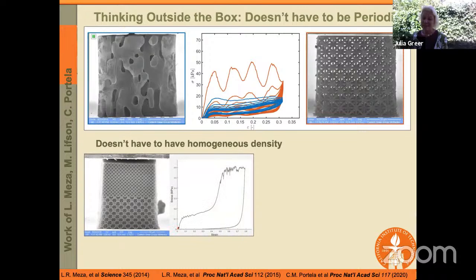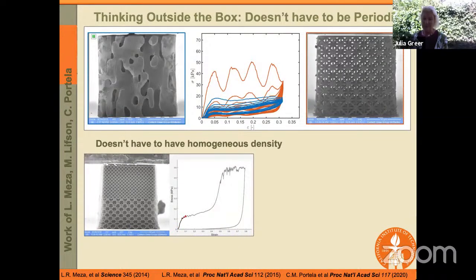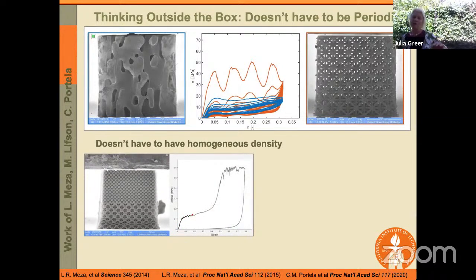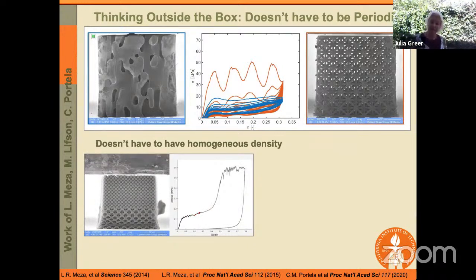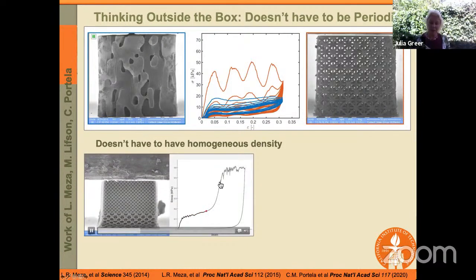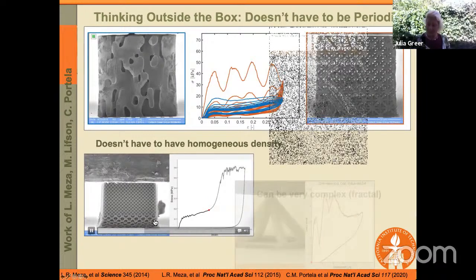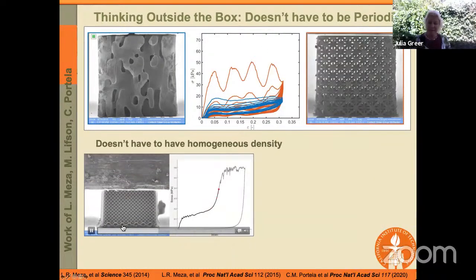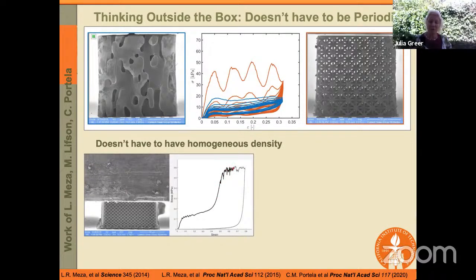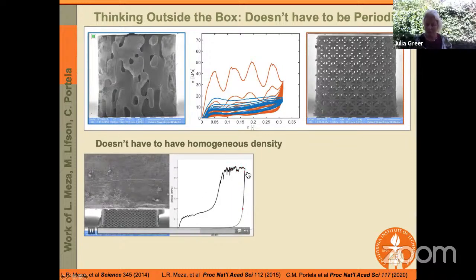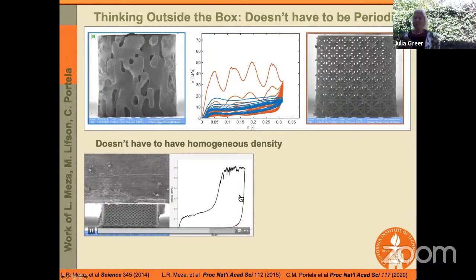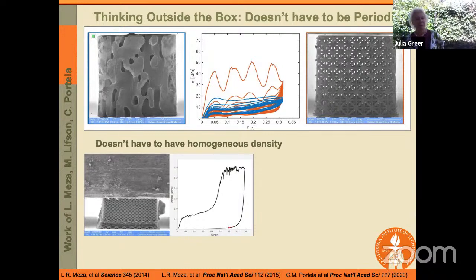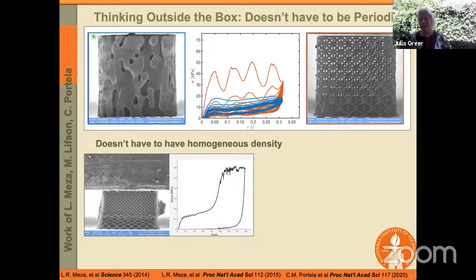Now, the density of these samples doesn't have to be uniform. In fact, you can prescribe trajectories of different densities and different designs into your architecture. So what you can see here is the example of two different densities, and you can see that the bottom part is fully compressed and densified before the top part even starts feeling the effects of the compression. And that is reflected in the stress strain data as well. So you can see the two different plateaus. So that teaches us that we can prescribe the different deformation paths and perhaps suppress failure in these kinds of materials as well.